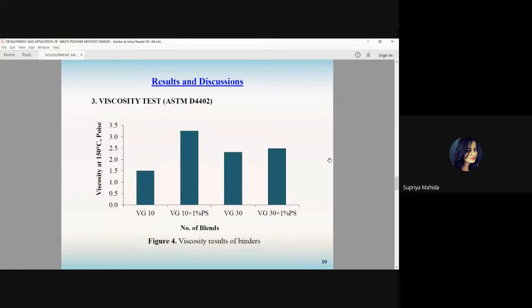Then we performed the viscosity test. It is done with the help of a Brookfield viscometer, and we followed ASTM D4402. The viscosity test is conducted at 150 degrees Celsius, and we found that the viscosity of the thermocol binder is increased compared to the conventional one. So at 150 degrees Celsius, there is ease of mixing the binder with aggregate for preparing the modified mixtures. We can mix at the same temperature with the modified binder, and we have that ease of mixing, so the proper coating with aggregates will be done at 150 degrees Celsius, giving a very good composition of binder and aggregates.